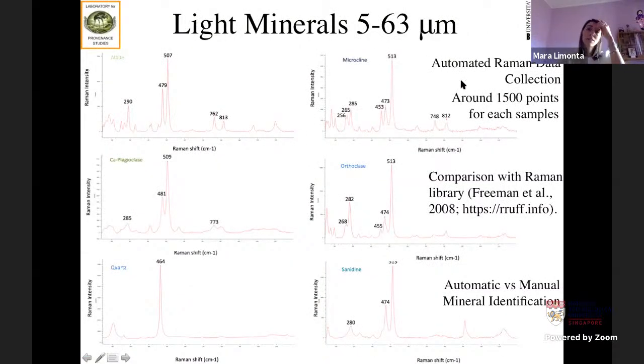From the light minerals, we use an automated Raman collection, around 1,500 points for each sample we analyze. And what we can do, thanks to Raman spectroscopy, is to identify different minerals, analyzing the diagnostic peaks of different mineral species. And we compare our spectra with the reference spectra. Here you can see what we use. And here you have some grains that we analyzed.